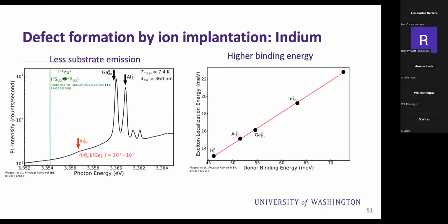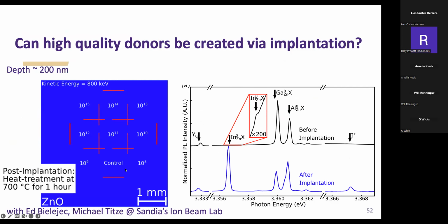The first result that's happened in the past year is that we can form these by ion implantation and annealing now. So here is a zinc oxide substrate, synthetically grown, where we can see the gallium and the aluminum and the indium. We chose indium to have minimal interference with the gallium and aluminum in the substrate. There's only a tiny bit of indium in our substrate. And we had no idea what levels to implant. So we implanted up to visibly damaging the material, to not being able to see it above the substrate emission. But what you can clearly observe is where the indium line was before. Here it's multiplied by 200-fold. Now we have a very strong indium emission peak by implantation and annealing the indium.